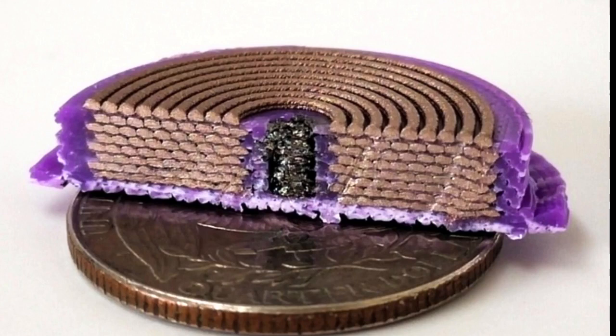Due to the added precision of the modified printer, they could make solenoids that were about 33% smaller than other 3D printed versions. More coils in a smaller area also boost amplification. In the end, their solenoids could produce a magnetic field that was about 3 times larger than what other 3D printed devices can achieve. While these solenoids can't generate as much magnetic field as those made with traditional fabrication techniques, they could be used as power converters in small sensors or actuators in soft robots.